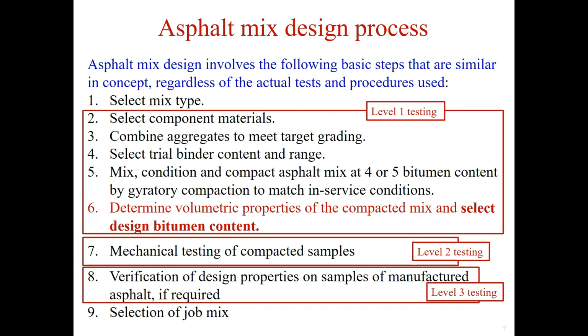Step 2 to 6 belongs to level 1 testing. Step 7 is the mechanical testing, or level 2 testing. Step 8 is the verification test, or level 3 test, to check the air voids or wheel tracking results of the asphalt samples.